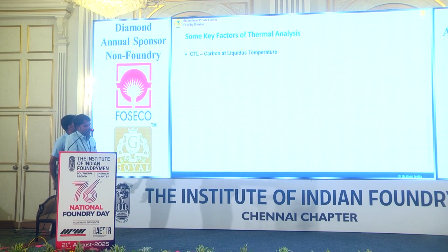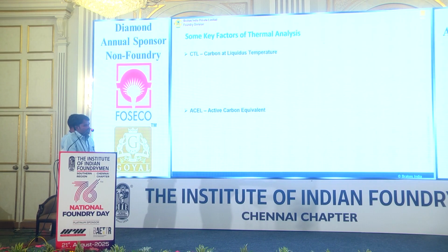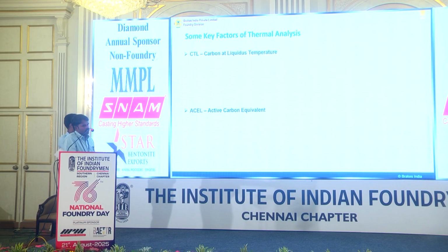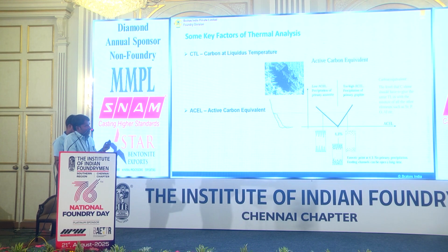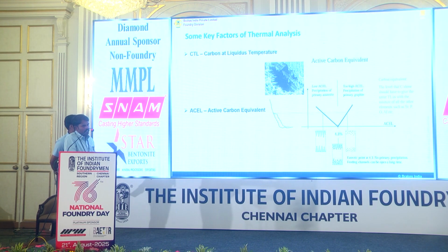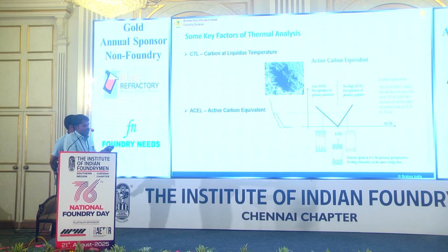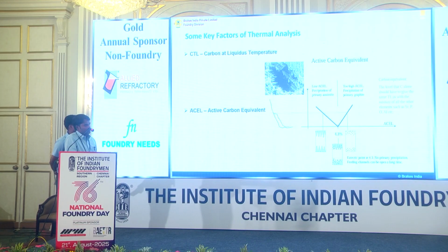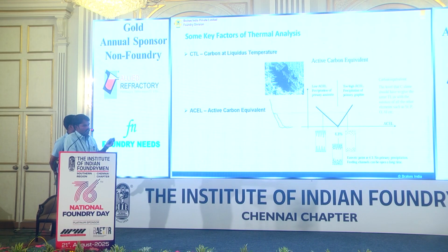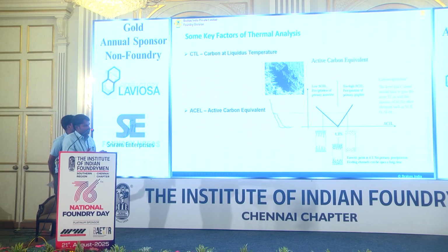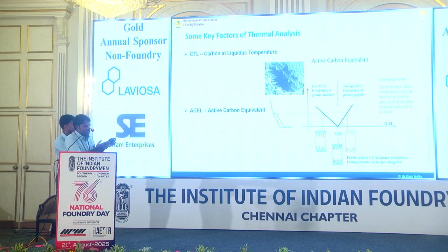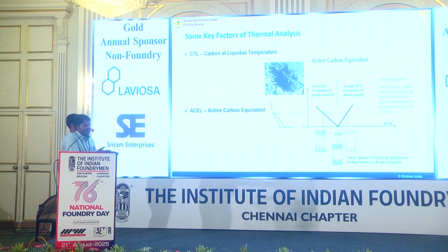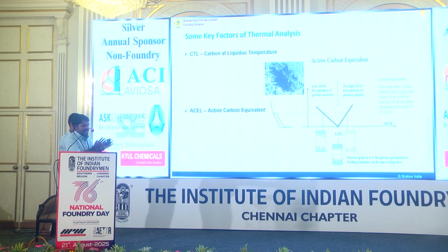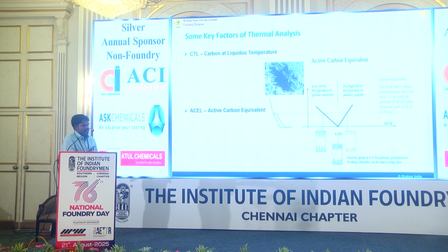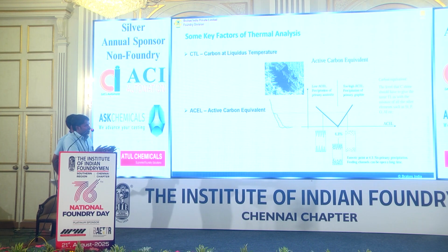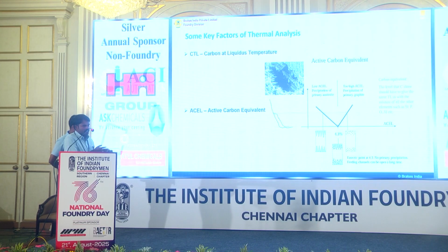Other key parameters in addition to these thermal analysis parameters are carbon at liquidus temperature and the active carbon equivalent. Active carbon equivalent can be found only in the thermal analysis system, not through the spectrometer. Even when we achieve a carbon equivalent of 4.4 or 4.5 by calculating in the optical spectrometer, it will show differently in the thermal analysis system at 4.3 or 4.25, which is the actual active carbon equivalent, rather than the one shown in the spectrometer. So it is a very important parameter to know the precipitation of graphite in ductile iron.